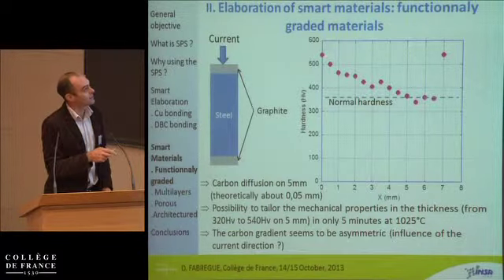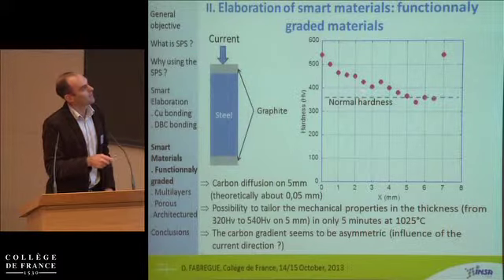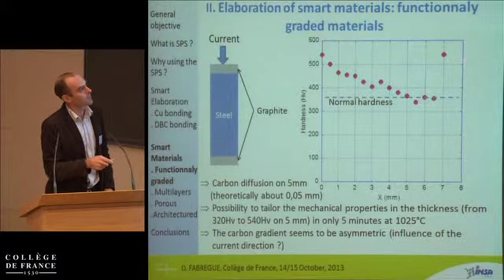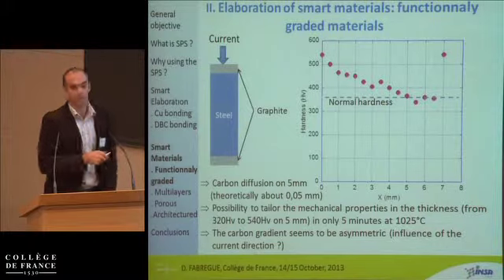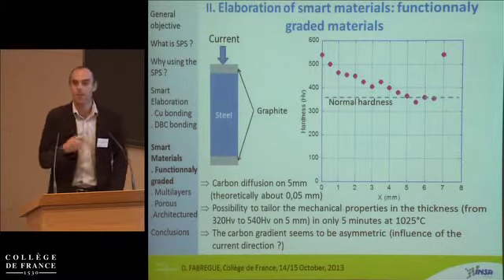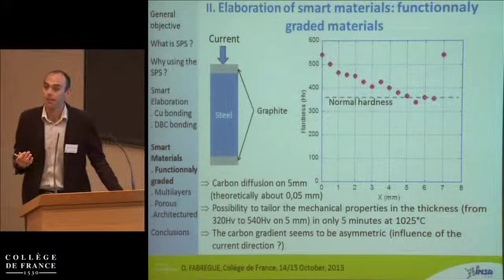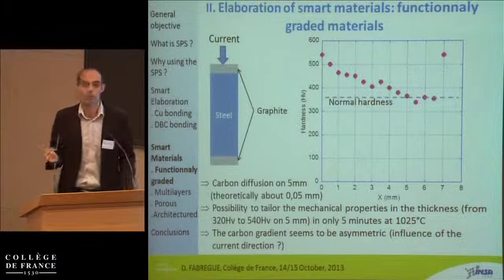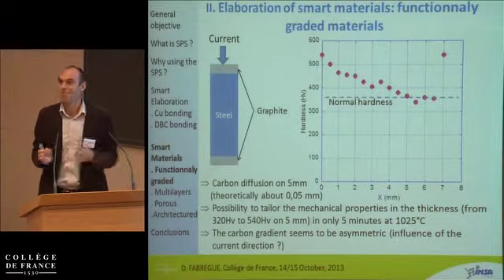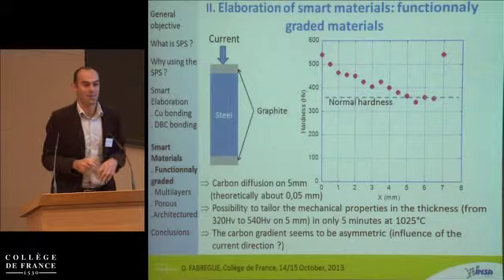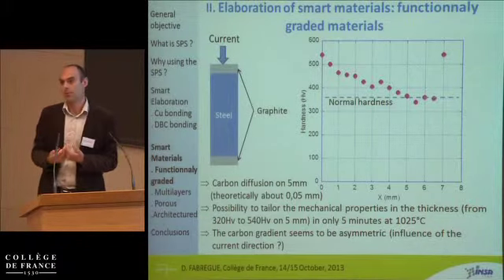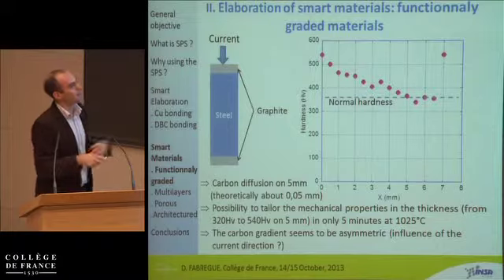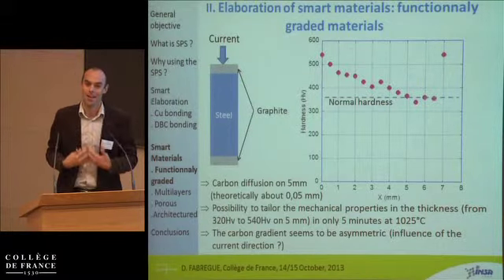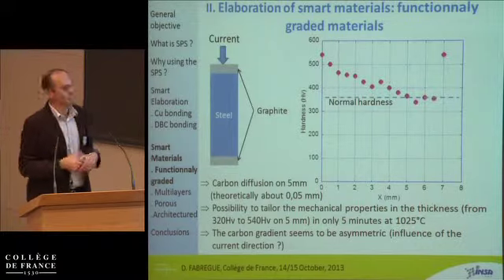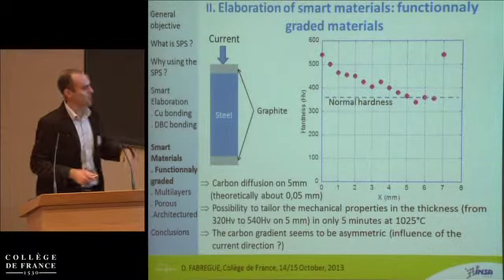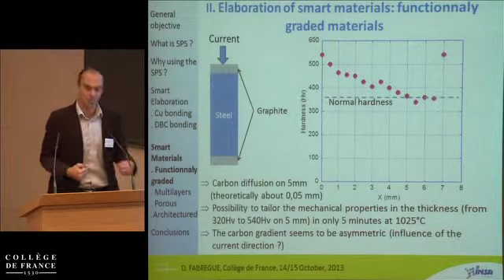Now you also see something very strange: here the diffusion is about, let's say, 4 to 5 millimeters, but on the other side, it's less than 1 millimeter, which is exactly the size you would expect from the normal diffusion coefficient. Maybe it's still under examination, but it seems to be the effect of the current direction. Here the current is going in one direction and enhances the diffusion, and on the other side, it may even prevent it, actually. I won't show some results here, but you can prevent the diffusion if we want to.